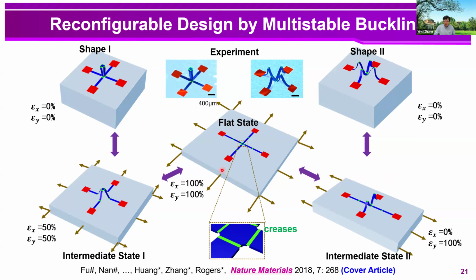At the center shows a crossing precursor design, which is attached to a biaxially pre-strained substrate. And here the green color denotes the creases with reduced thickness, and the red color denotes the bonding site. Here, if you release the biaxial pre-strain simultaneously along two directions, the structure will follow this deformation path, and finally you will get this shape 1 mode.